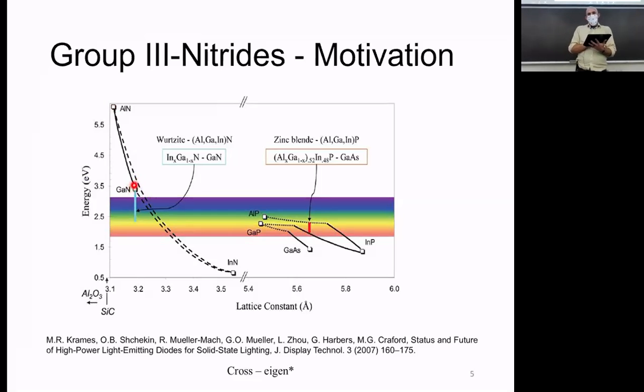Gallium nitride is sitting at about 3.4 eV over here, which is just above visible, but we can drag it down ever so slightly into the visible, and that then works very well for emitting light like the LEDs that we talk about. Indium nitride is all the way down here, and it was discovered to have a band gap of about 0.7 to 0.9 eV in 2000, so fairly recently.